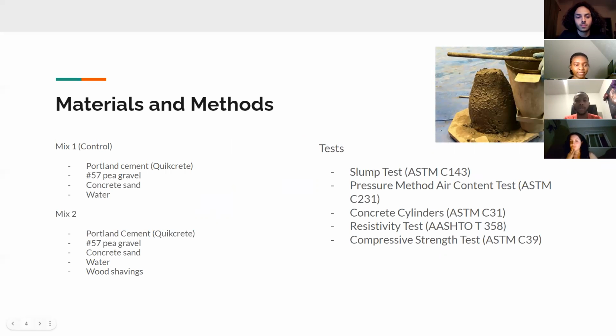So for our experiment, we created two concrete mixes, mix one, our control mix, and mix two. The ingredients for mix one were Portland cement or Quikrete, number 57 pea gravel, which was the coarse aggregate, concrete sand, which was the fine aggregate, and water. The ingredients for mix two were the same as mix one, except for the addition of wood shavings.